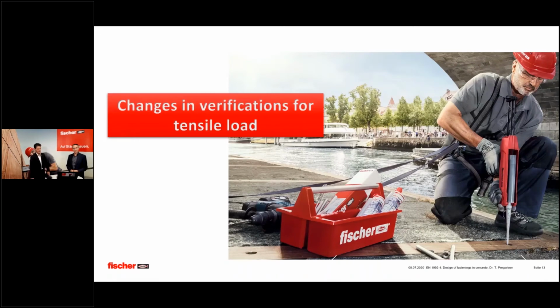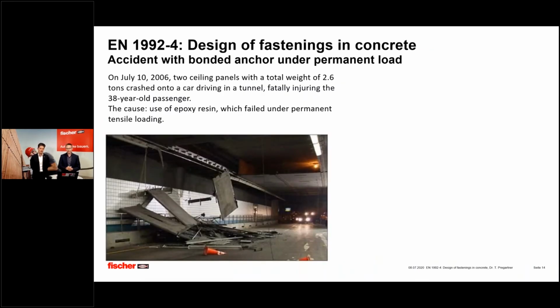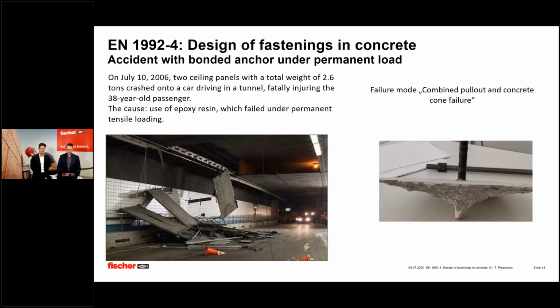Good. Now let's have a look at one of the most important changes if you look at EC2 Part 4 in total, compared with the guidelines before. These concern verifications for tensile loads and especially adhesive anchors. The reason for these pretty big changes in terms of anchor design was an accident that happened in 2006 in the US in a road tunnel in Boston, where ceiling panels fell down on a driving car and a passenger got killed. The root cause for this failure was the use of an epoxy resin which failed under permanent tensile loading. This accident caused a lot of additional research in the world of anchors.